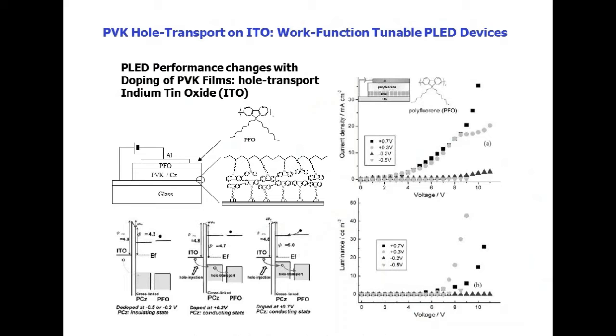So, for example, we've reported on utilizing polyvinyl carbazole grafted on an indium tin oxide layer, which is useful for solid-state display devices such as LED or even solar cells. In this case, what we've done is we've successfully grafted polyvinyl carbazole and improved the blue emission properties and lowered the turn-on voltage of polyfluorene, which is a standard light-emitting polymer. This goes way back more than 10 years ago when we started this work.